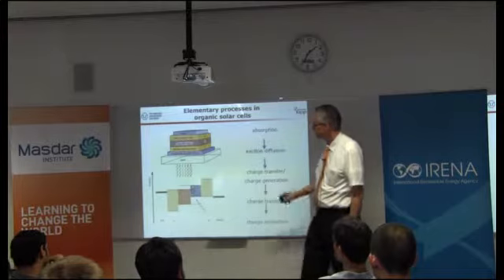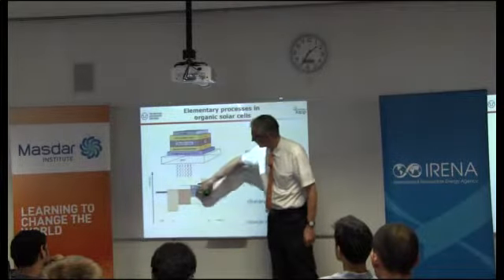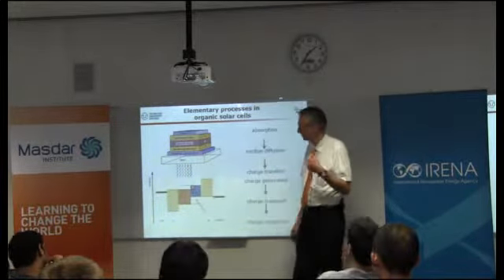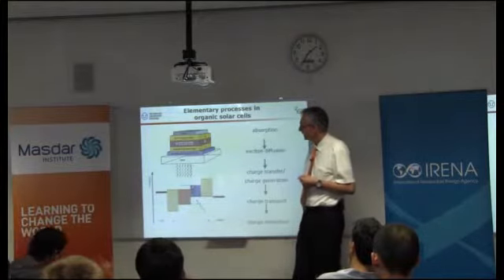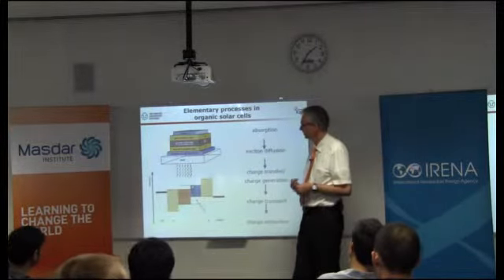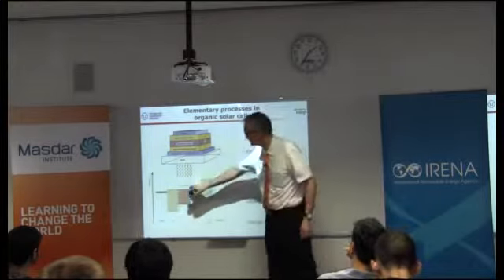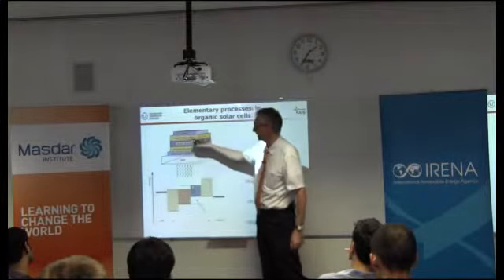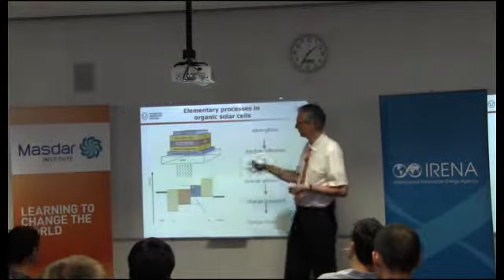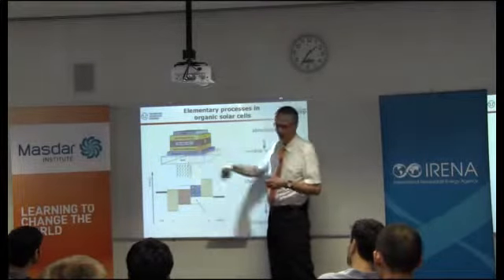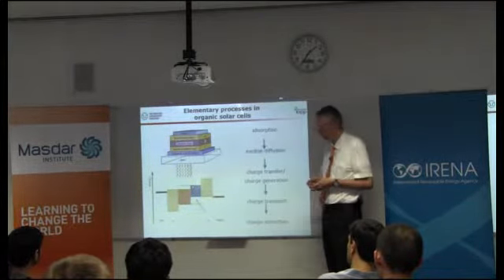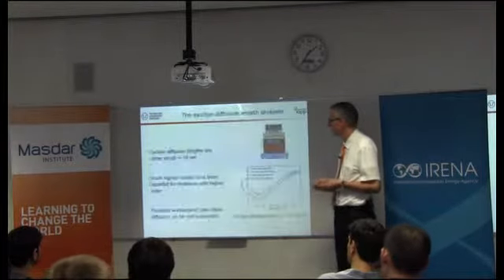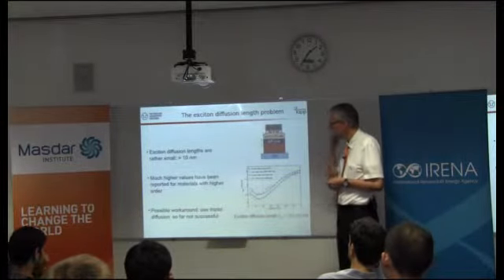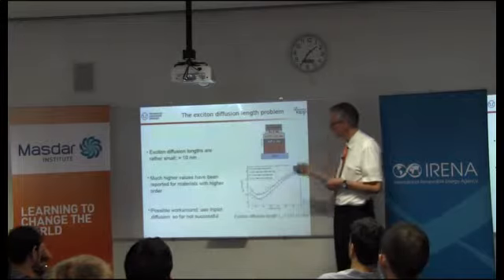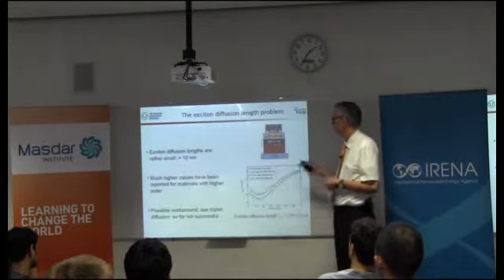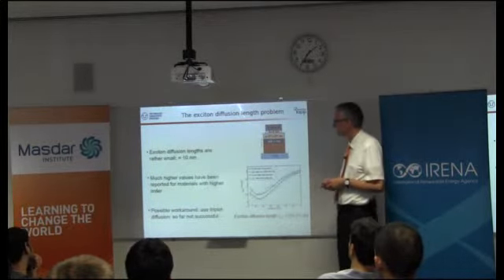And unfortunately, the distance these excitons can move is small. It's on the order of 10 nanometers only, which is much shorter than the absorption length. So what you do is you mix these two materials in a so-called bulk heterojunction. So you have a nanomorphology with different paths. And this nanomorphology is the big challenge, to control that and optimize it. Here are some data for the diffusion lengths. We've measured some by modeling in an organic material.